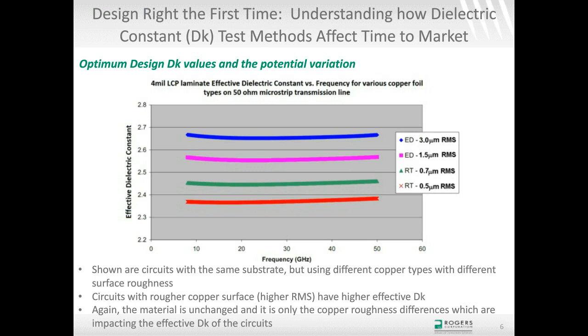What we get is the effective dielectric constant on the y-axis and frequency on the x, and you can see that the circuits using the smooth copper, the red curve, which has a copper roughness of about 0.5 microns RMS, had the lowest effective dielectric constant. And it's a very distinct trend there. The circuits using the little bit rougher one, 0.7 microns RMS, green curve, have a little higher effective dielectric constant. And you get the idea. The one with the highest surface roughness is the blue curve, 3.0 microns RMS, and that had the highest effective dielectric constant. There's a difference of about 0.3 in effective dielectric constant while using the exact same substrate.